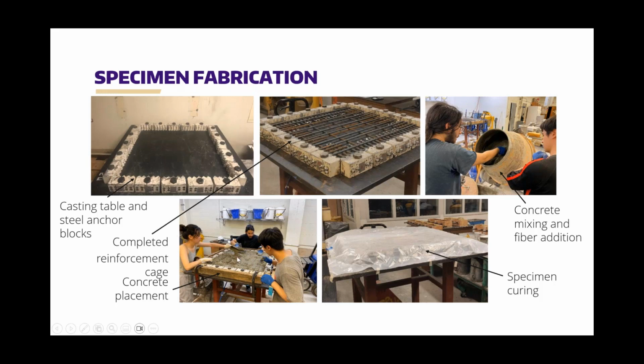So we had an external vibrator that helps to consolidate the panel. We found out later in the test series that we also needed to use a little bit of internal vibration along the edges of the panel to make sure we had really good consolidation around the edges.